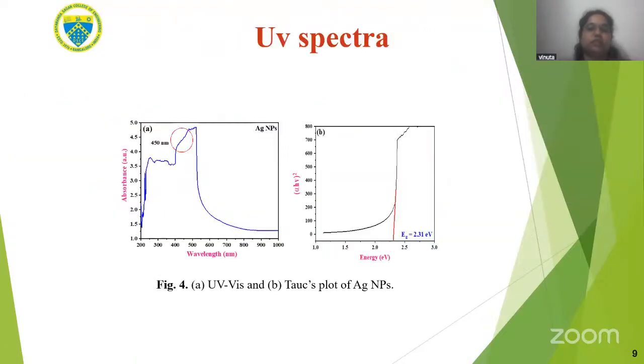Synthesized silver nanoparticles UV spectra were recorded and Tauc plots were drawn. So the UV visible spectrum shows that the generation of silver nanoparticles was confirmed by the surface plasmon resonance band centered at around 450 nanometer.